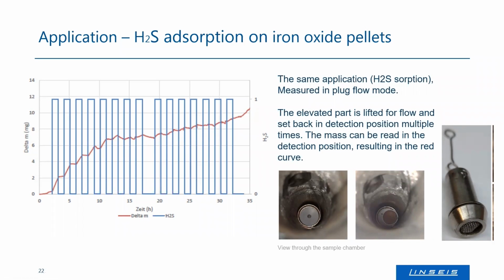And this kind of setup is absolutely impossible in a classical thermal balance, because there, of course, you would have to place your balance in the way of the flowing gas. However, in the classical balance, you would have a lot of influence on your weighing signal and a lot of disturbance as well. And that's a clear advantage, where the magnetic suspension balance can be operated in a way that the classical balance can't be.